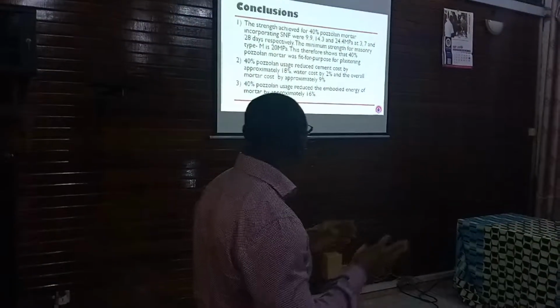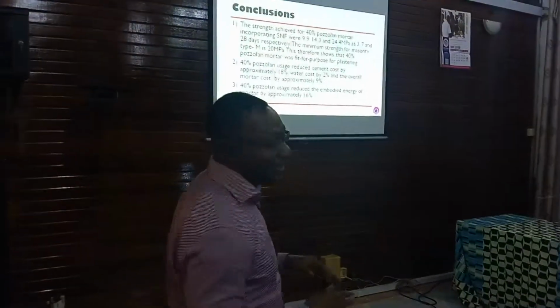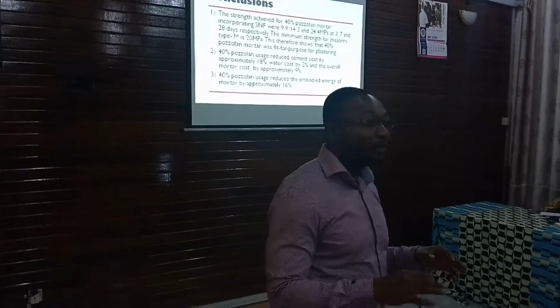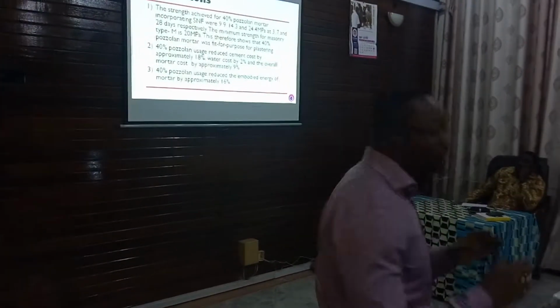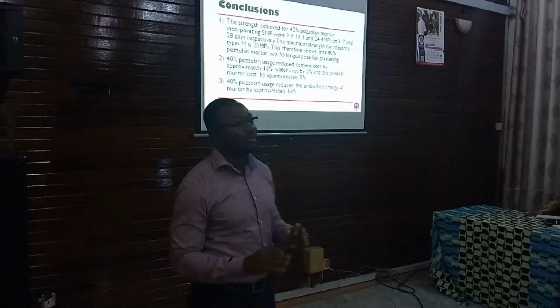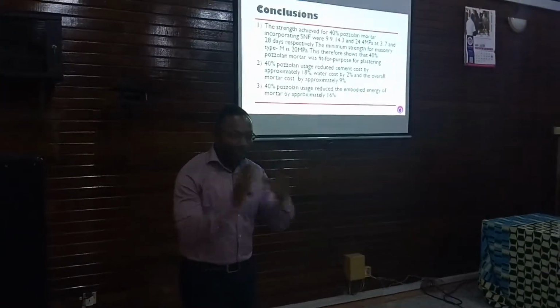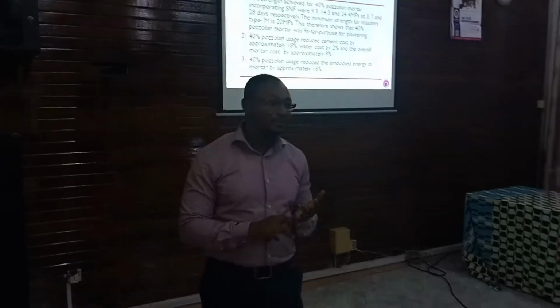So you just apply the standard. Now, the 40% usage reduced cement costs by approximately 18%, water costs by 2%, and the overall mortar costs by approximately 9%. Now, at 40% pozzolan usage, the embodied energy of the material was reduced by about 16%. So these are the 3 strong conclusions I want to bring to the fore: embodied energy, cost reduction, and then the strength of the material.